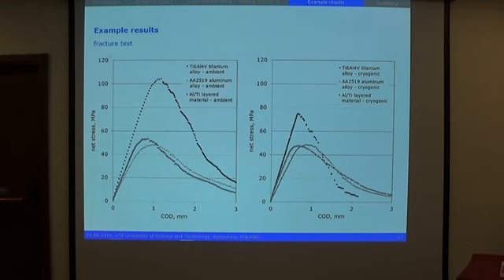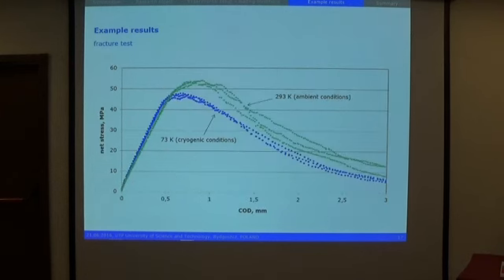And for cryogenic condition, of course, the parameters describing the fracture toughness are lower than for ambient temperature. And here is the comparison of our layered material, the comparison of the results of the test. Here is the net stress, not the force, because the cross section of all of the specimens was not the same value, and it gives us a better condition for comparison of the results.